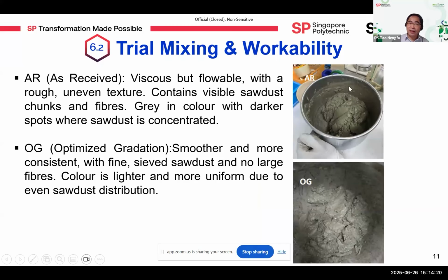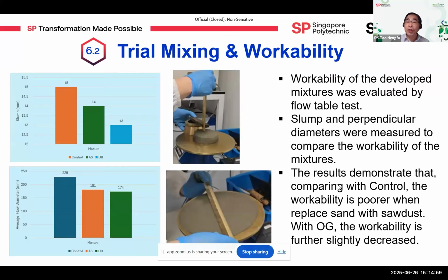the photo here shows the AR cement mortar, which is viscous but flowable with a rough, uneven texture, containing visible sawdust chunks and fibers. Gray in color with darker spots where sawdust is concentrated. The photo below is an OG cement mortar mixture, which is smoother and more consistent with fine sieved sawdust and no large fibers. Color is lighter and more uniform due to even sawdust distribution. Workability of the developed mixture was evaluated by flow table test.